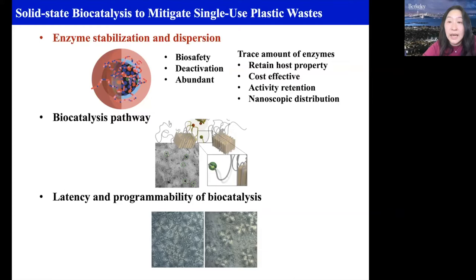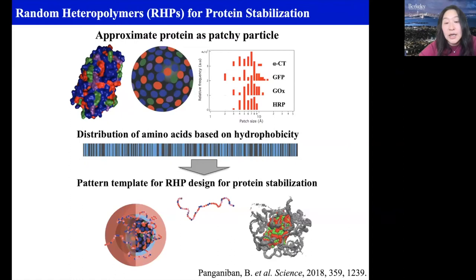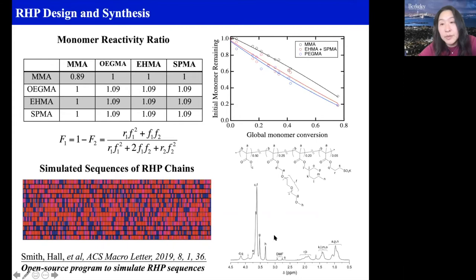The first thing is we have to disperse enzyme inside of the plastic at the nanoscopic level. And that turned out to be non-trivial because you really have to keep the enzyme active while enhancing compatibility. And we have a field advantage here because my group developed a technology back in 2018 where we basically put a little plastic wrap around the enzyme, allowing us to maintain the activity in a non-native environment. If you look into what that wrapper is, we purposely went with methacrylate-based materials.